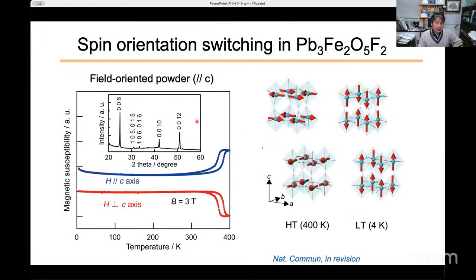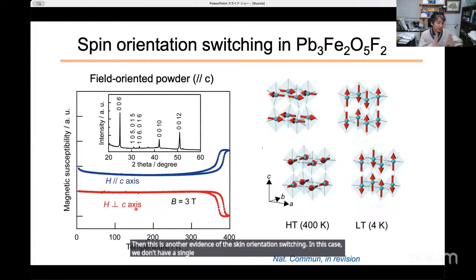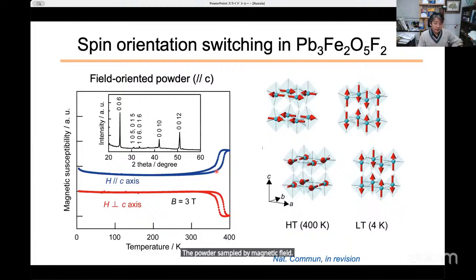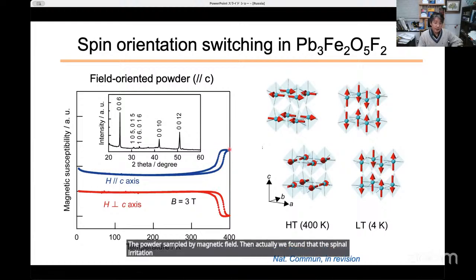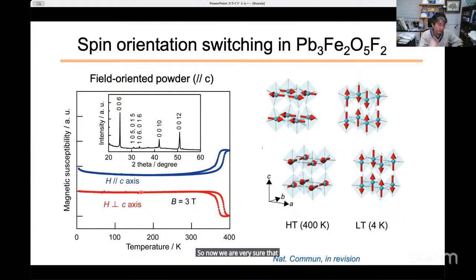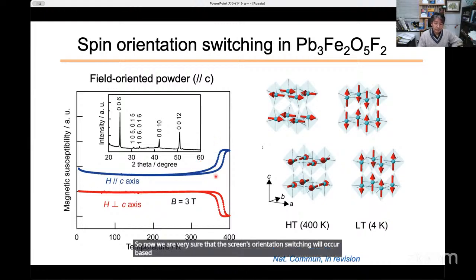Then this is another evidence for the spin orientation switching. In this case, we don't have single crystals, but we actually oriented the powder sample by magnetic field. Then actually we found that the spin orientation depends on the magnetic field applied. Okay. So now we are very sure that the spin orientation switching occurs based on structure phase transitions.